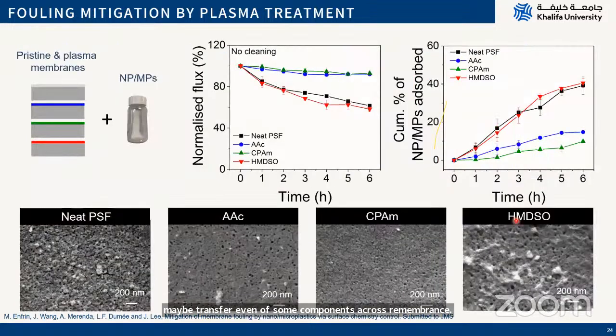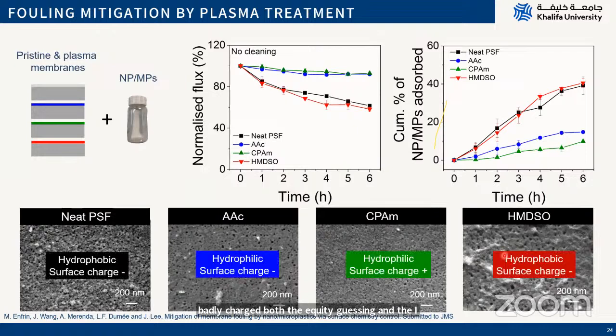We did the fouling studies just like before, and we found the cumulative amount of microplastics adsorbed was varying a lot, and we had two control groups. The membranes having the silicone and the neat PSF polymer had much more adsorption. The other two had much less. So changing and controlling the charge to have more extremes seemed to help repel some of these microplastics. However, you could still find some fouling. When the PSF was very badly fouled, both the acrylic acid and the amine-rich monomer were okay, and the HMDSO also had a lot of fouling happening.